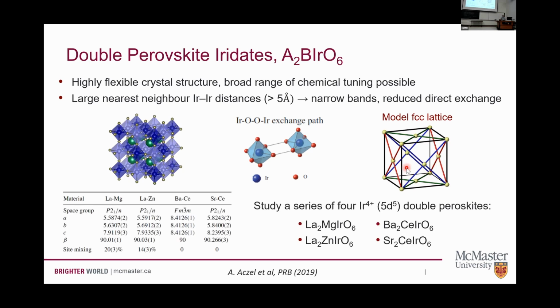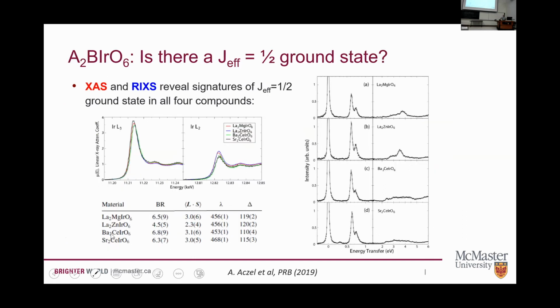Okay, so we wanted to study a series of these different double perovskite materials. We picked this set of 4 because they gave us different degrees of structural distortion. So we can tune the spacing, we can tune the shape of the local iridium cage, we can go from monoclinic to cubic, we can put in a little bit of site mixing or a lot of site mixing and see how these things affect what we see in terms of their Kitaev properties. What we find is that these sort of subtle structural details don't really have much of an effect at all.